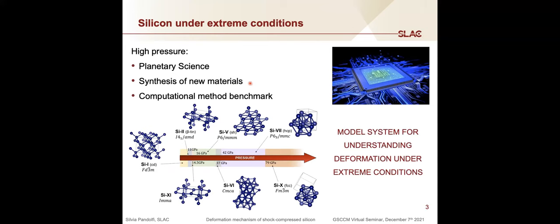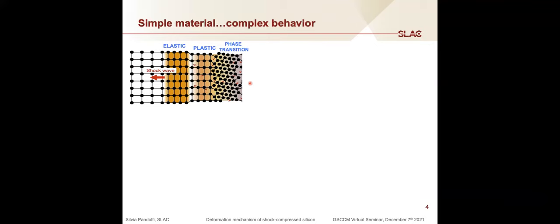And of course, another very interesting thing about silicon is that because we've used silicon so extensively in industry right now, it's a material for which we can very easily have samples with negligible defect concentration. So it's actually a very good starting point if we want to gain new insight and acquire a deep understanding of the deformation mechanism at extreme conditions at an atomic level, because we know that we can have samples for which the effects of defects in the starting material are negligible. So despite being such a well-known and relatively simple material with this FCC structure, silicon, when under extreme conditions, in particular under shock compression, exhibits a pretty complex behavior.